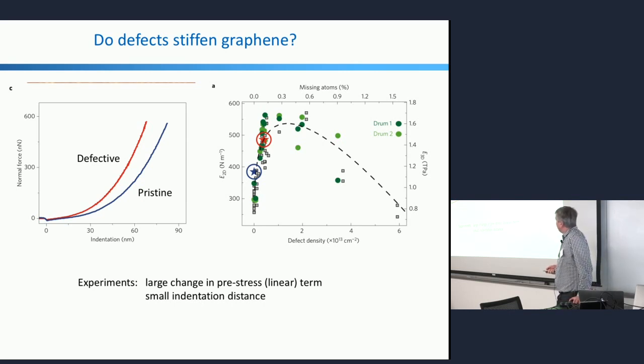I look at these experiments and it's one of those things where you just get a funny feeling, but you can't say why you think something's funny. But I do notice a few things. One is that the pre-stress changes a little bit, and so when you're doing this fit, you always have to be careful if one term changes. The other thing is that this indentation distance is not tiny, but it's not quite as large as one would like, and this force is still a little bit lower. They're going nowhere near this kind of maximum breaking load. Right? But I can't point to one thing and say that is definitely wrong experimentally.